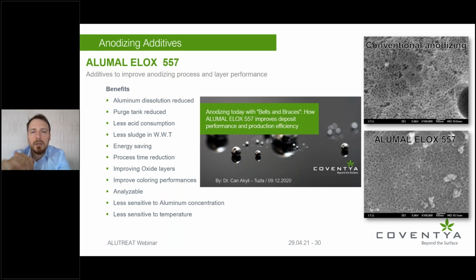And if need be, the process can be adjusted to give you a more glossy surface, so a more transparent oxide layer, or to provide a harder layer that can be achieved even at elevated temperatures, like 10, 15 degrees Celsius higher. So it gives you a much more robust process, which is easier to control, and therefore enables you to apply higher current densities, higher sulfuric acid levels, and higher temperatures that would help your production by preventing any burning of the layer.